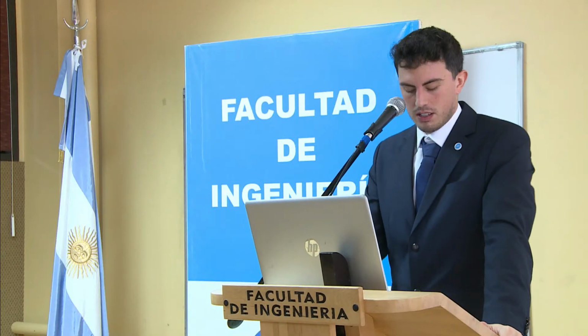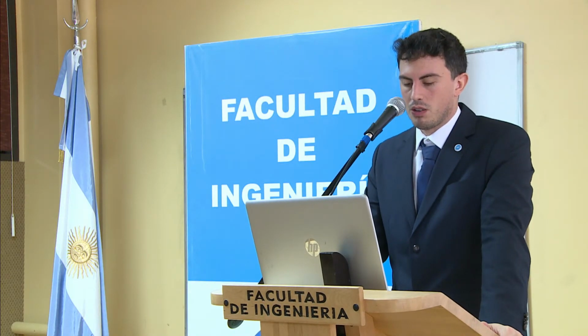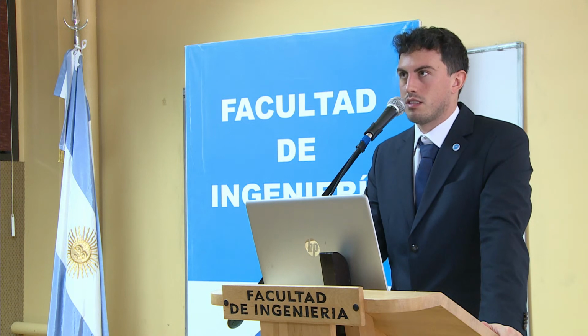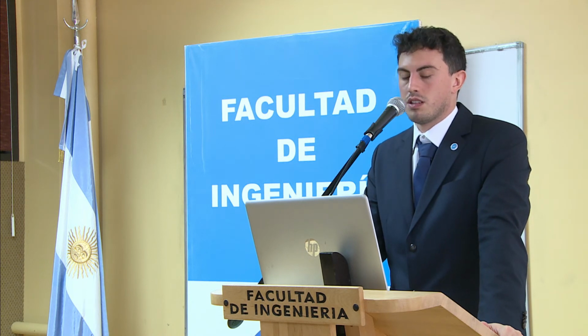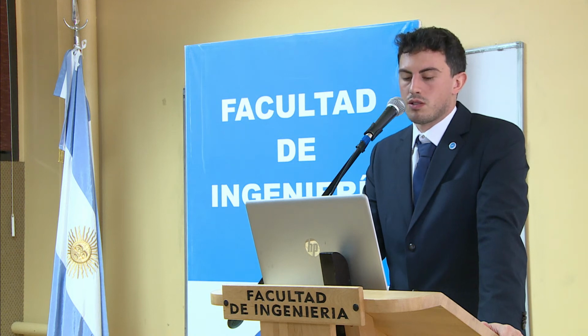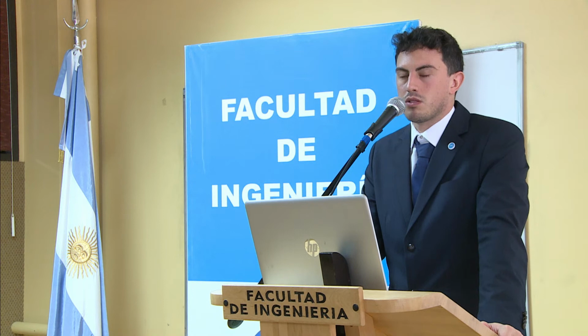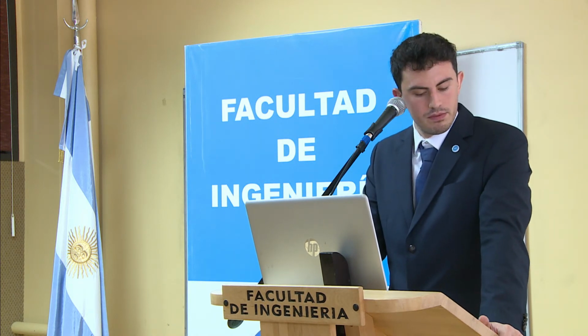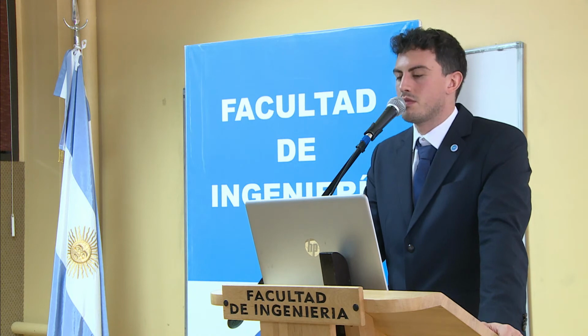Yeah, I mean, having a very low porosity makes it harder to saturate this sample, and in some cases when we were performing the isotropic test, the pore pressure was not going up, so we were not able to calculate the Biot coefficient in that case. Okay, thank you.